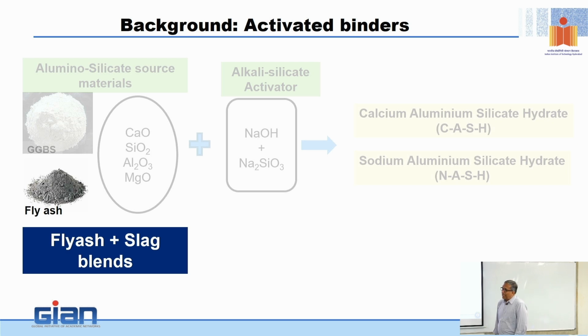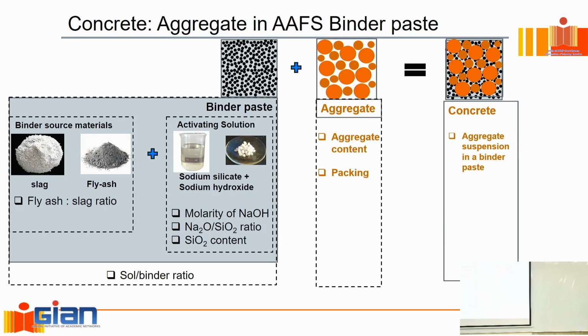So the more accepted terminology is AAM. We just call them alkali activated materials, to avoid the confusion. Now, you looked at a similar figure for cement paste. When we looked at concrete made with cement paste, we drew a line and said everything that is not aggregate goes into the paste. Now, if I look at a concrete made with an alkali activated fly ash slag binder, I would have a binder paste, which is my fluid medium, and aggregate. Just like before, the two things of concern are the aggregate content and the packing. Whatever the objective of packing was in the exercise you had yesterday, it remains the same here. Nothing changes as far as that goes.